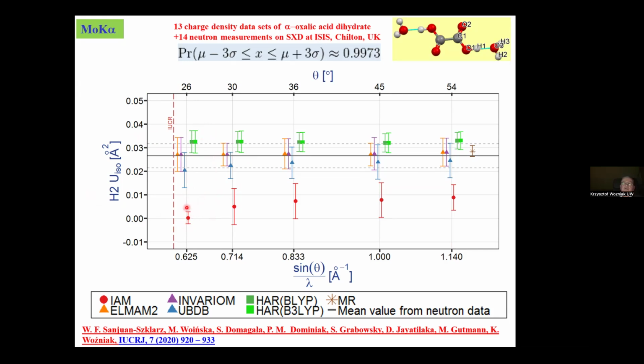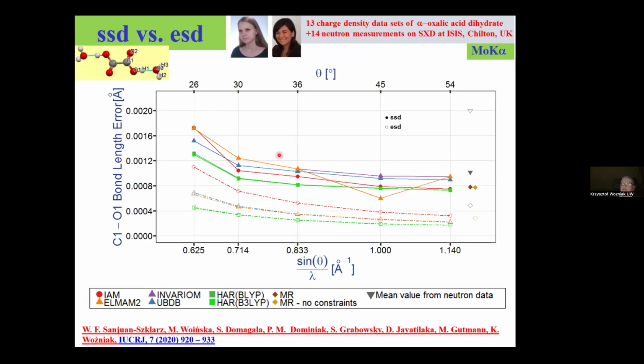Actually, of course it's best to use Hirshfeld atom refinement, then the results will be correct anyway. But when somebody is sticking to the independent atom model, one should also correct temperature factors. And this is the dependence for errors, for sample standard deviation and estimated standard deviation. Estimated standard deviations we are getting from least squares procedures, but they are only showing us how errors of the input variables are transmitting into the errors of the final results.